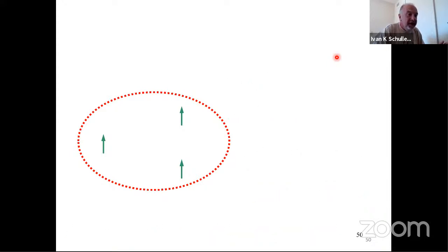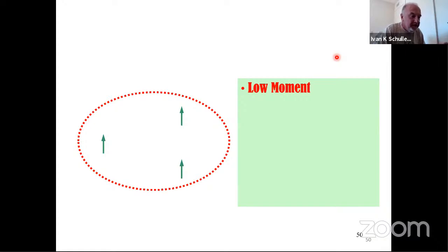And so therefore, the way to think of this is like a ferromagnet that has a low moment because it has very few spins. What I mean by low moment, we can actually calculate it based on the exchange bias, is about 5% of the antiferromagnetic moment. Remember, always, the green spins are spins which are part of the antiferromagnetic lattice, but because of the defects, they are uncompensated. The rest of the spins in the background are still there, but they're fully compensated.